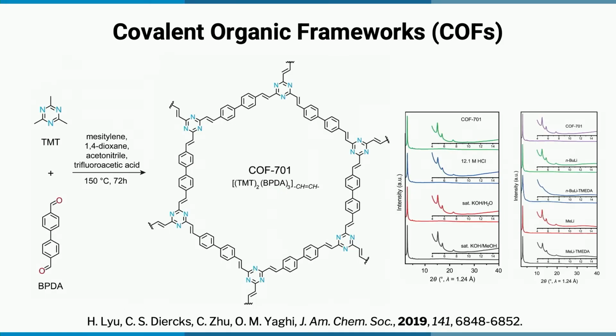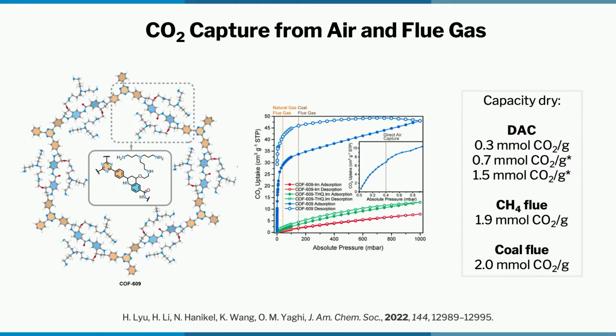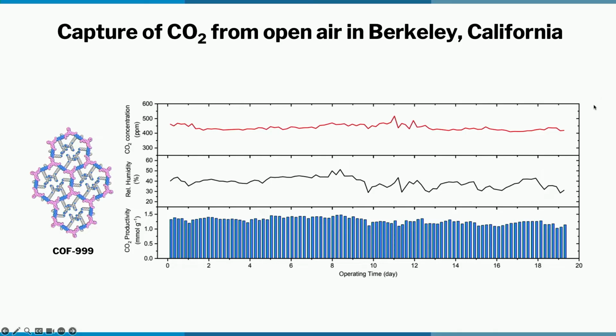But COFs can. We worked very hard on making very stable COFs since 2005. And the latest is that you can make a COF out of carbon-carbon bonds and carbon-nitrogen bonds, some of the strongest bonds in chemistry. And you can make crystalline structures of this kind. I just have here the powder diffraction to show the crystallinity, but also the stability in 12 molar HCl, very strong acid, saturated KOH, even corrosive media like n-butyllithium. This is the kind of stability you need to have a material that's going to be in a power plant for a long time.